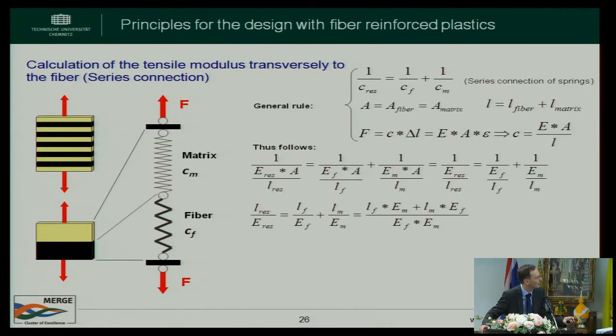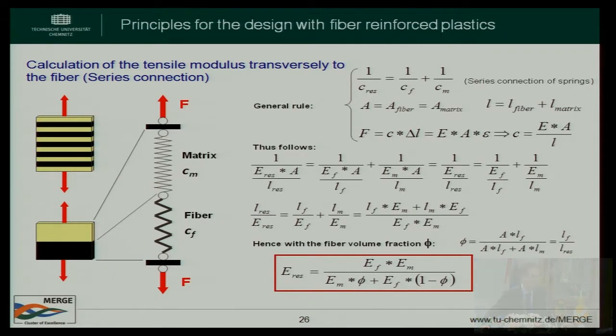And now, if you look in the fiber reinforced plastic perpendicular to the fiber, it's something like a series connection of a stiff spring of the fiber and the matrix. So the load is more or less the same going through all. The matrix also has to take the same load as the fiber, and therefore you can imagine that there's a big difference if you have a load in fiber direction or perpendicular to it. Okay? So the resulting tensile modulus is calculated totally differently from the tensile modulus of the fiber reinforced plastics in fiber direction.